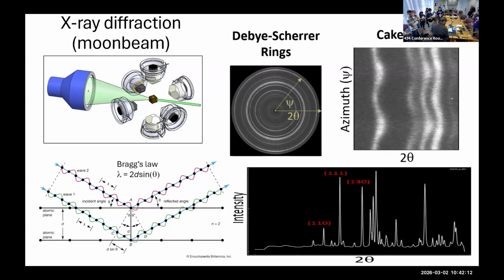So I should say, what happens is we're doing powder diffraction. So we don't actually use powder, we use like sintered rocks. But they're made of powder originally. So think of, you have like 1,000 grains that are in your diffractive beam path. So imagine you have a grain. So these lines are going up and down, and you get your spots, like the two that are on the outside there. But now you have a grain that's oriented this way, and your spots are going to be up and down. And then you'll have a grain that's oriented this way, and another one that's this way, and so on and so forth. And you have so many grains, they're all coming out at the same angle though.